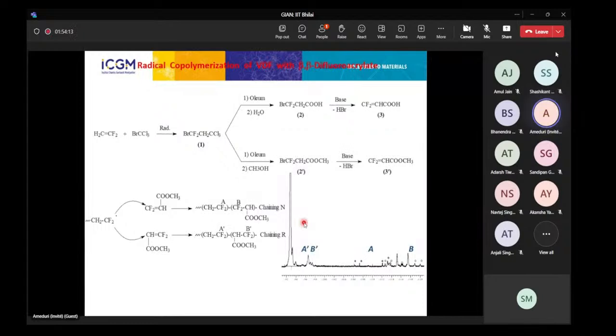fluorine NMR spectrum, showing that when you have a macroradical terminated by VDF, you have a chance to react onto the less hindered side, CF2, but it's a little bit big because the fluorine atoms are bigger than that of proton, or let's say the more hindered side here. And we have found that A prime and B prime are here, and A and B are here. You can see the little star I put here with a very nice system because of the presence of an asymmetric carbon here. So the two fluorine are non-equivalent as well as these two fluorine.